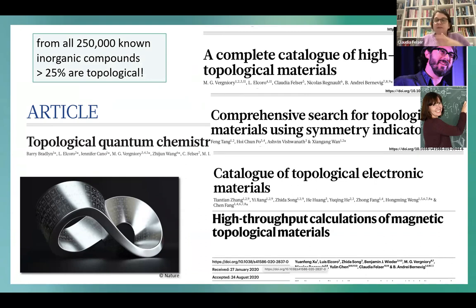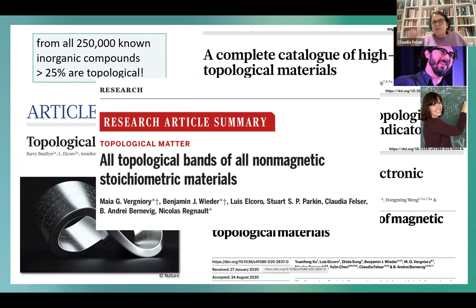There was a recent paper in which even magnetic materials were identified as topological or not. And I'm sure that in Heusler phases there are many interesting topological materials. You simply have to look them up. Especially if you allow for doping and changing the Fermi energy, because you always have overlapping bands between S, P, and D and different symmetries, and this always leads to topological properties.